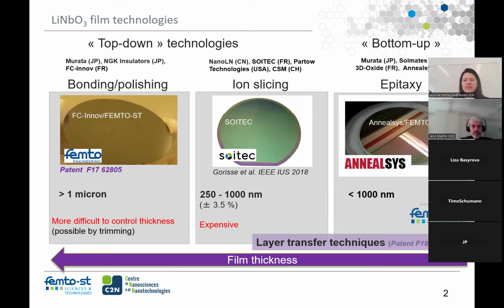And then, of course, the thickness variation will be about plus or minus 3% across the wafer. The size of the films, of course, will be limited in these top-down techniques by available wafers, right? So 6 or 8 inch. Then it's always done from congruent lithium niobate crystals.